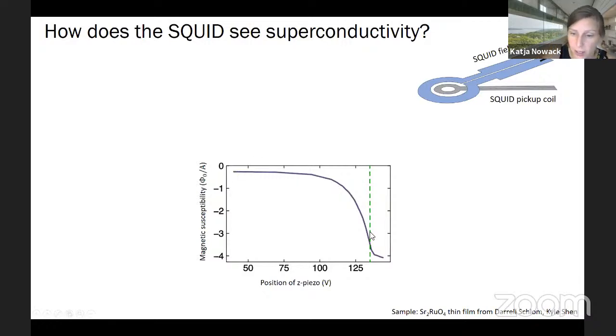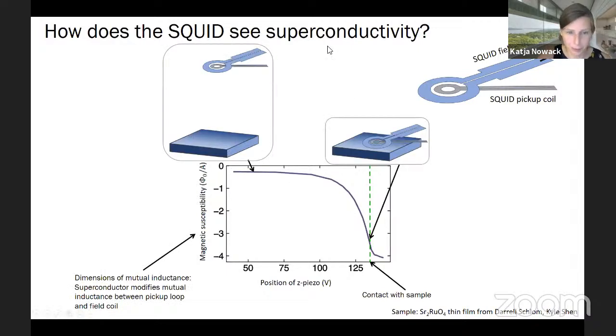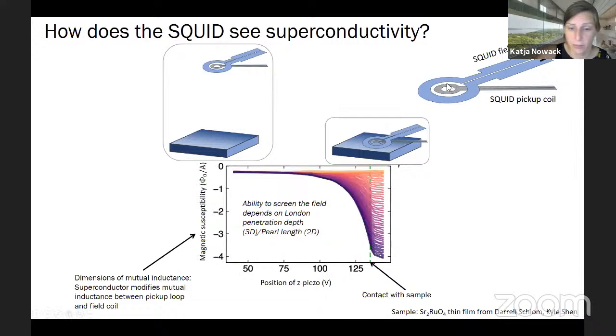But if we approach a superconductor, then the superconductor is going to start screening the field that is generated by the current in this field coil. We see this as a change in the mutual inductance between the two coils. And the closer we get, of course, the more dramatic that change is. So here we're far away, and here we're really close to the sample. The ability of the superconductor to screen the magnetic field depends on the London penetration depth in 3D and the Pearl length in 2D. Of course, if I change temperature, the dark trace was the lowest temperature, and the more pink to orange traces are taken as we increase temperature. As we increase temperature, the ability of the superconductor to screen the field is diminishing, and so we see a less and less dramatic effect on our mutual inductance.